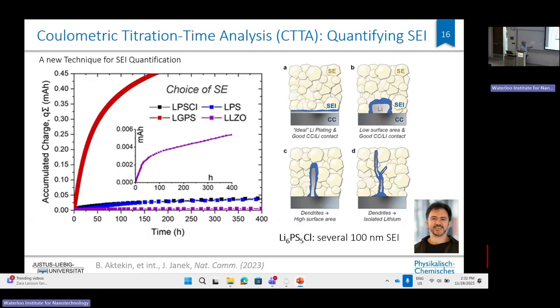And you see here different solid electrolytes. This is a famous oxide, lithium lanthanum zirconate. And this graph rarely consumes any lithium because it's simply stable. There's the lithium germanium thiophosphate. It contains germanium. Germanium is easily reduced by lithium, and it consumes lots of lithium, even within, let's say, 150 hours. The argyrodite, which is a lithium PS5 chloride, a sulfide electrolyte, is not so bad. It consumes, let's say, within 400 hours, 25 microamp hours per square centimeter, roughly. That's not so much, but it continues. So this is an issue.